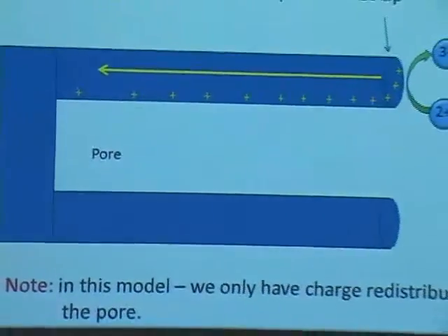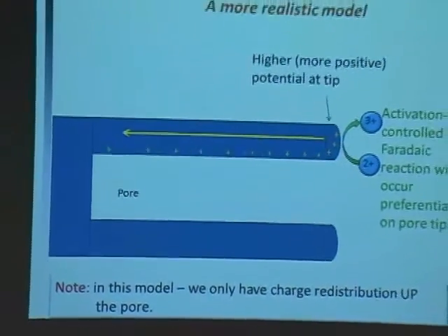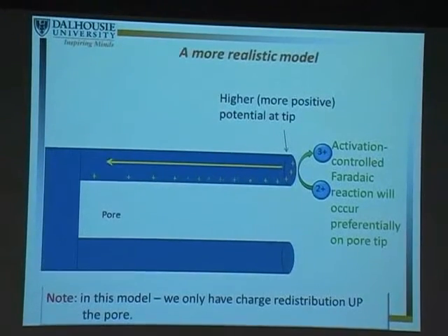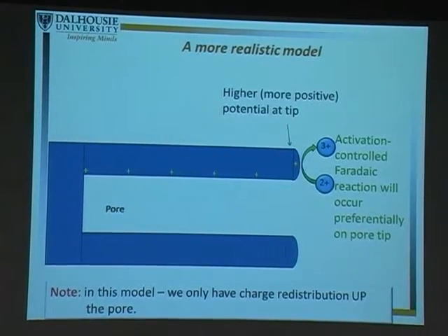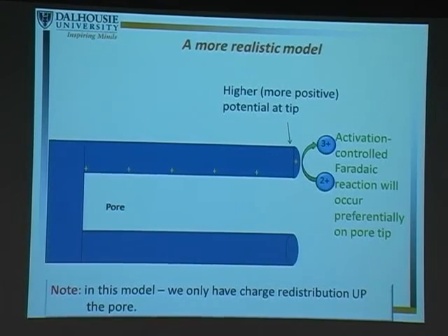So we wanted to make our model a little bit more realistic, and the way we did that is by now putting an activation-controlled reaction on the charge redistribution as well. So now we have that same pore. We are going to charge the pore, and we know that there's going to be a higher potential at the tip. And so the Faradaic reaction, whatever Faradaic reaction is occurring, is going to preferentially occur at those higher potentials, at the tip of the pore. And so we went back to our transmission line model.